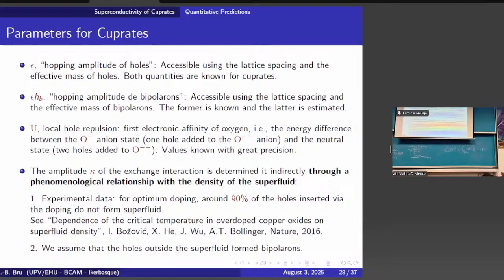So let me shortly explain. You have to fix this epsilon, the hopping amplitude of the hole. So you have h bar, you have the lattice spacing, you have the effective mass, so you can define what epsilon is. The hopping amplitude of the bipolaron is the same: you have the effective mass, the lattice spacing, you can define this. What is U? U is when you go from O minus minus and you add a hole. It's called the electron affinity of oxygen. It gives you a number.